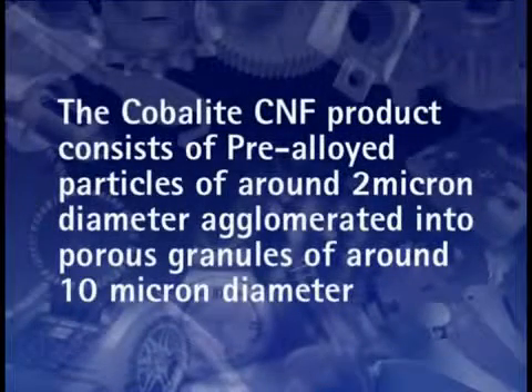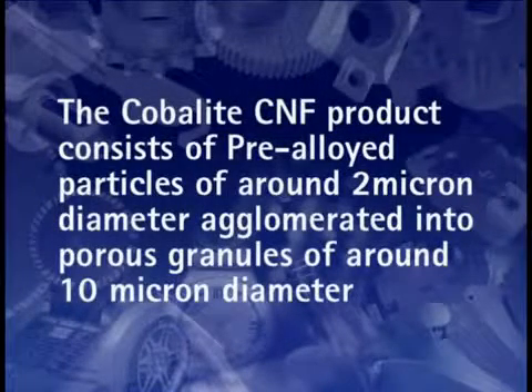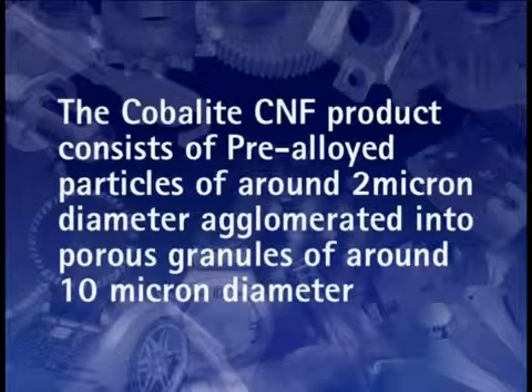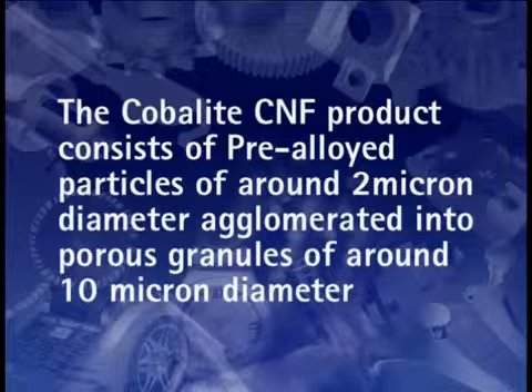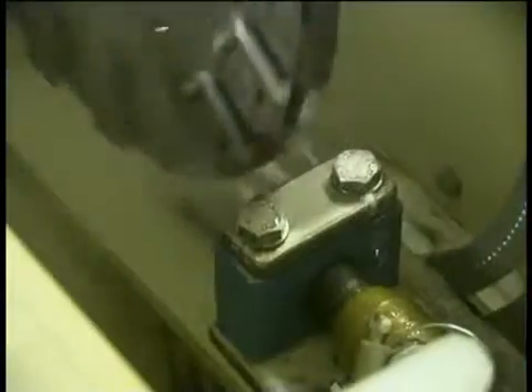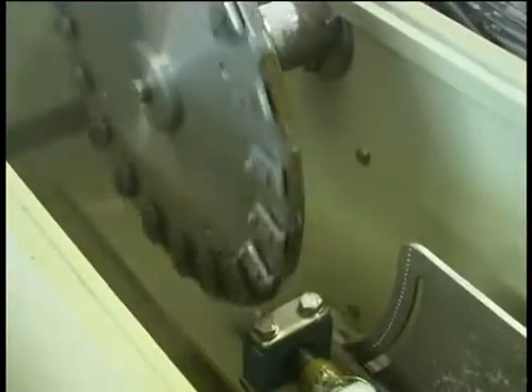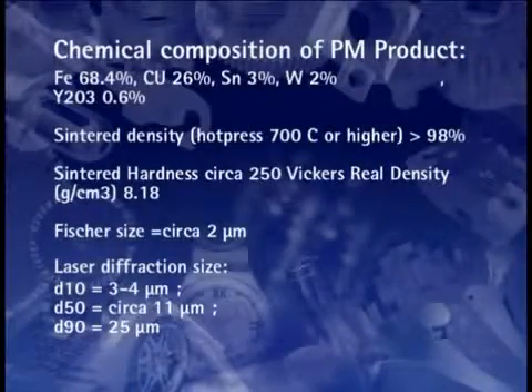The Cobalite CNF product consists of pre-alloyed particles of around 2 micron diameter, agglomerated into porous granules of around 10 micron diameter. Cold compaction at normal pressures gives green compacts of adequate handleability, better in fact than the reference cobalt powders normally used in this application. These are the properties of the material.